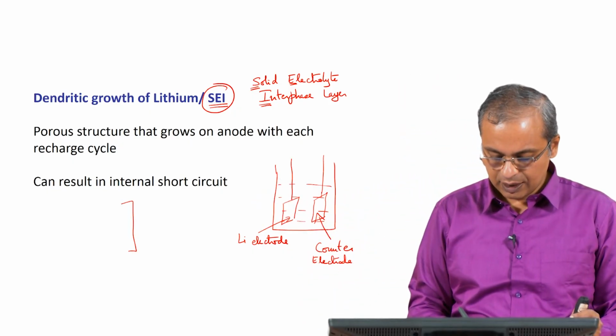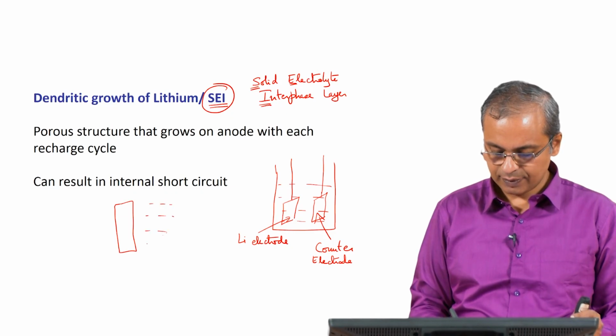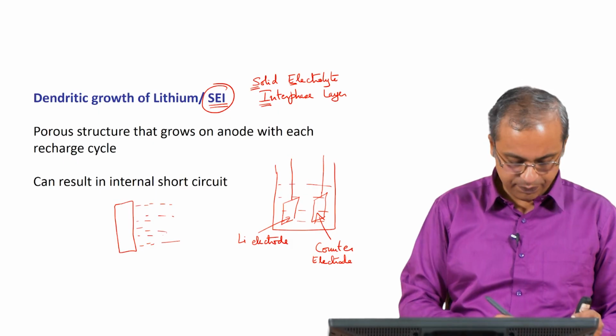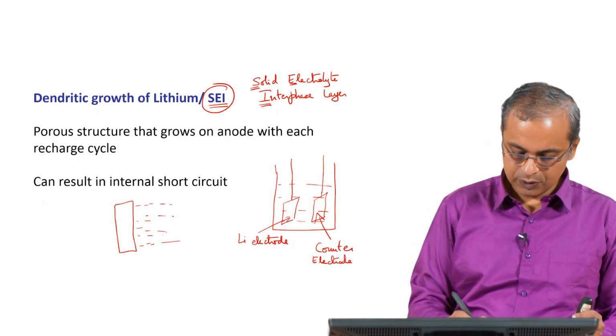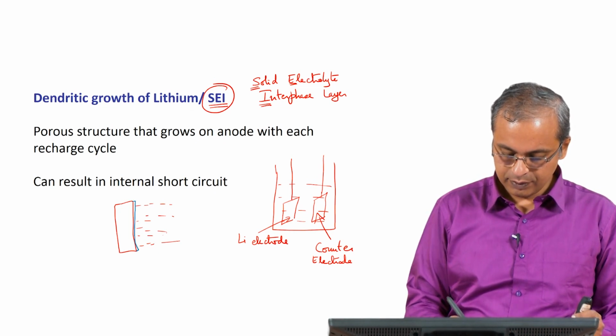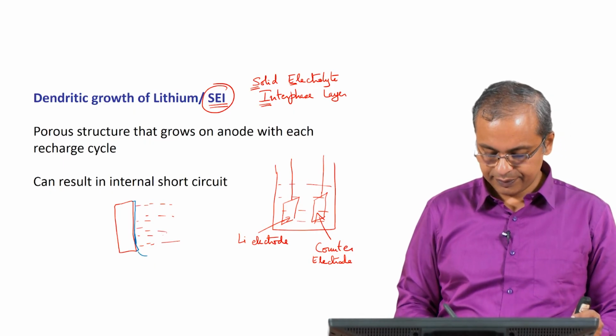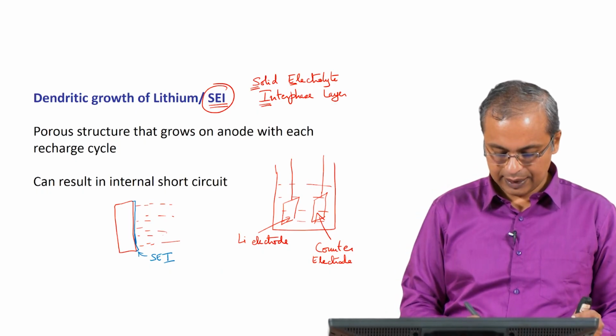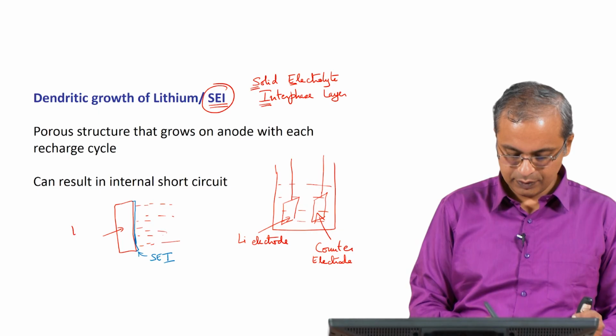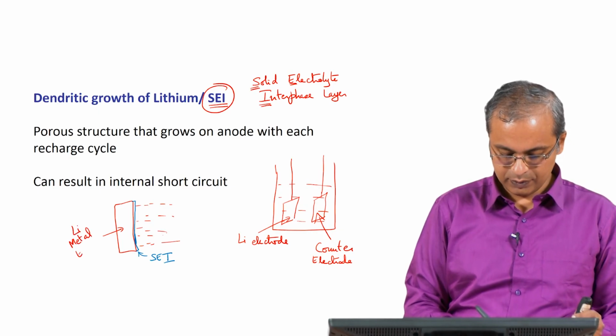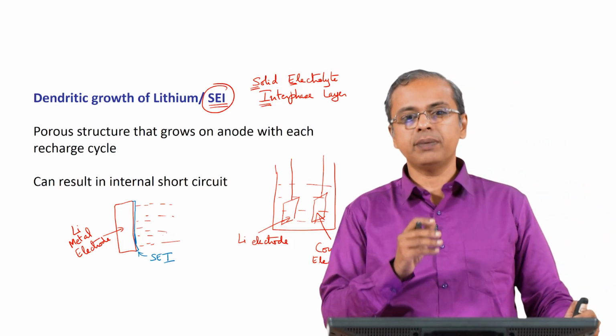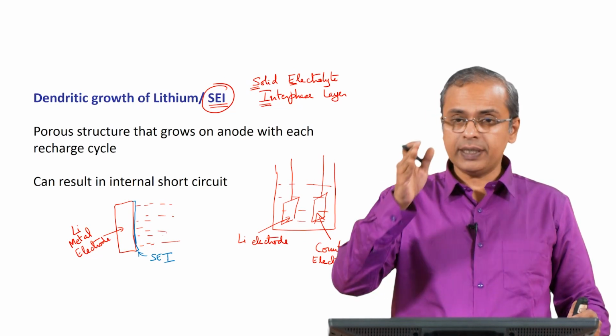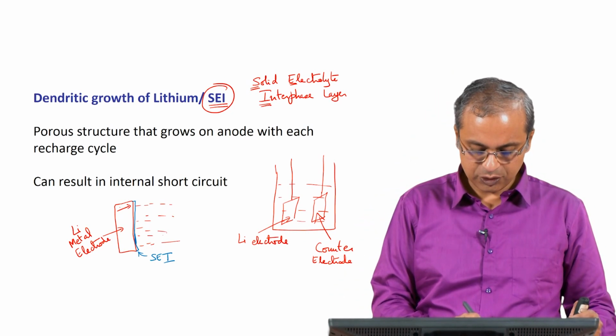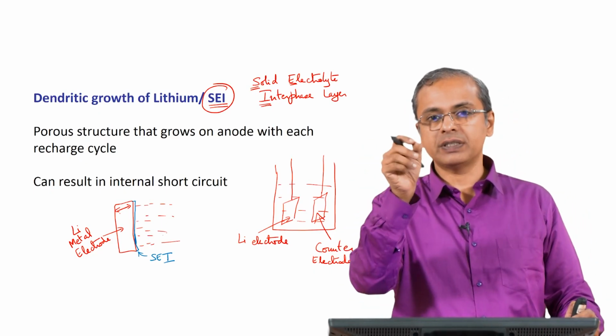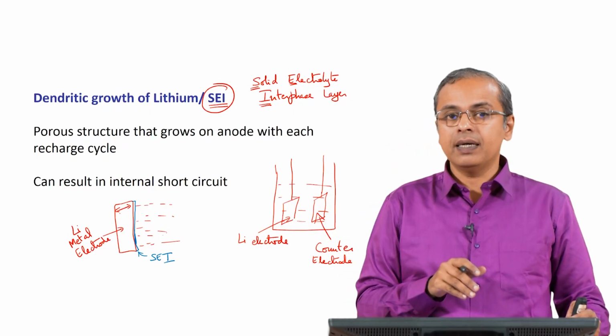So, for example, if this were the side view of the electrode and this is where the electrolyte is, the SEI will form at the surface. So, it will form right here. So, a structure like this will form. This is the SEI layer, this is the electrode itself. Okay, so the lithium electrode in contact with the electrolyte forms the solid electrolyte interface layer. So, it is good because this layer then protects the rest of the metal. Only the top layer of the metal which is in contact with the electrolyte passivates like this. So, therefore, the rest is protected.